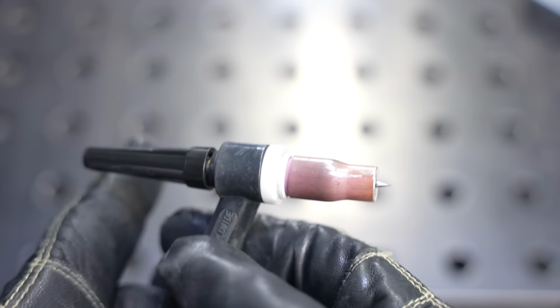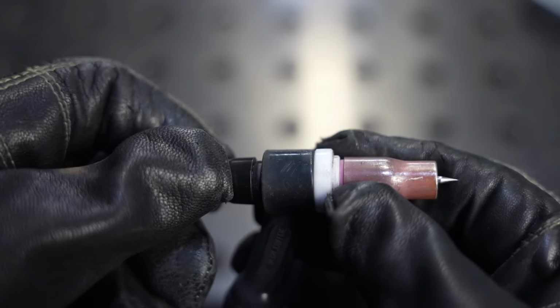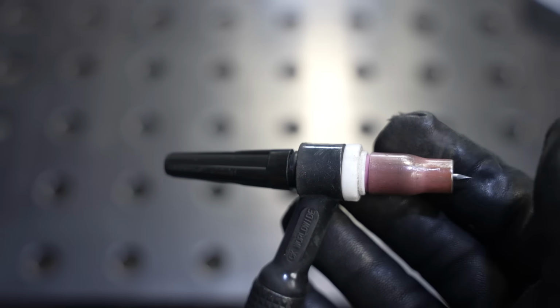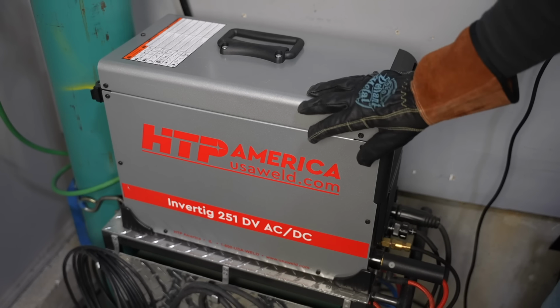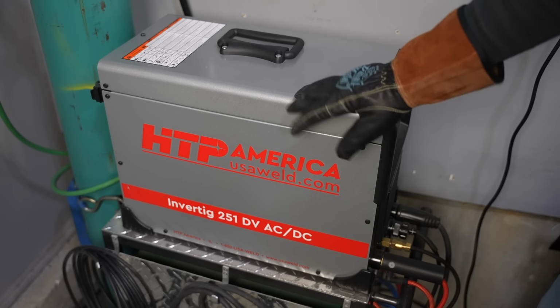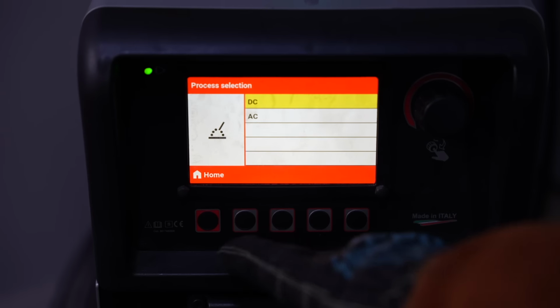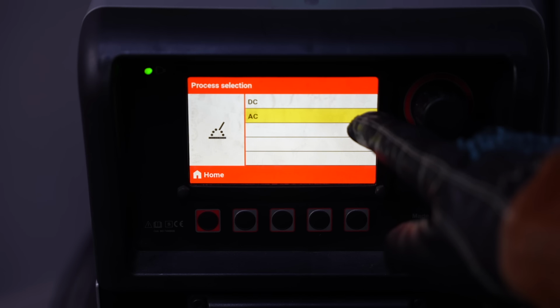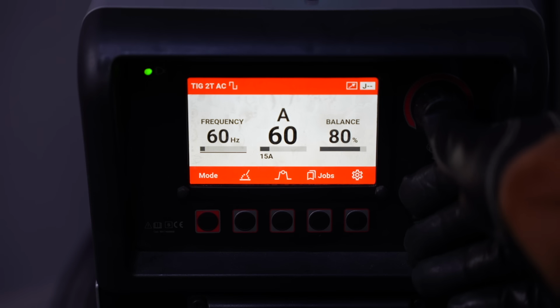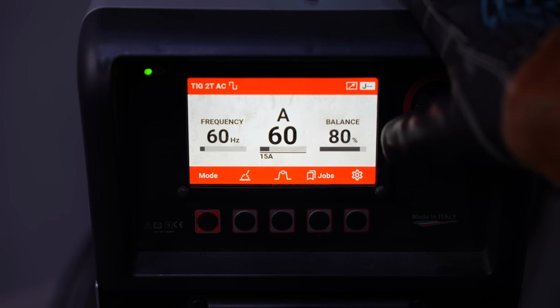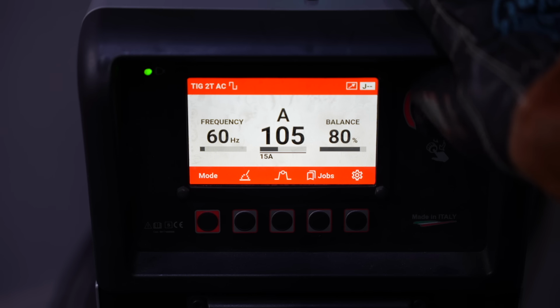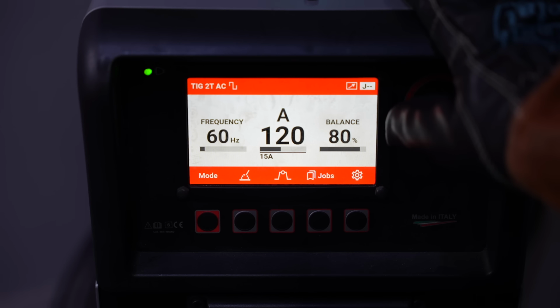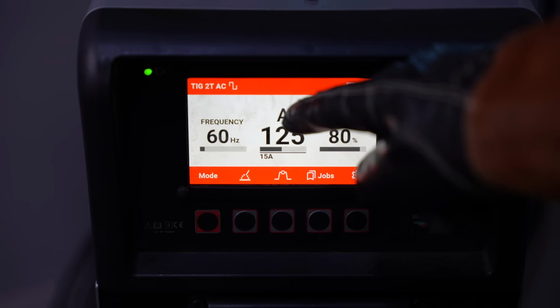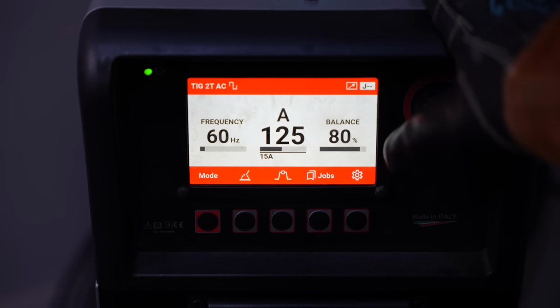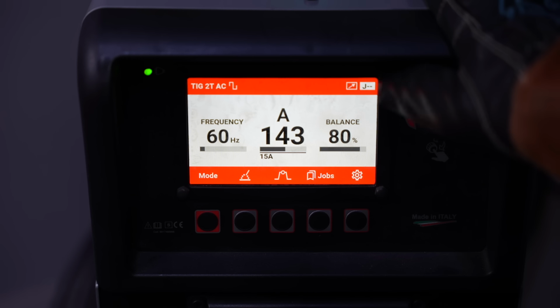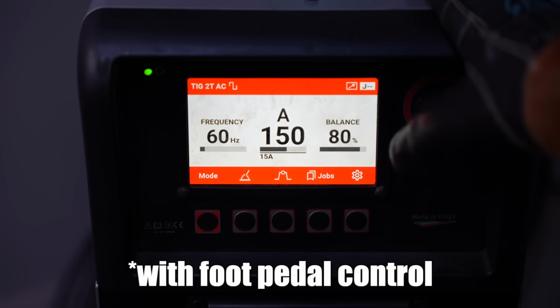Now, the actual extension of your electrode is going to depend a little bit on your joint type. This right here will be a pretty good middle of the road setup for me. This machine has all sorts of different ways that you can manipulate your waveform, but we're just gonna be using the basic setup here. When I go here, I can select AC, because I'm gonna wanna weld on alternating current with aluminum. And then I have 3 settings here: frequency, amperage, and balance. Now, amperage, a good rule of thumb is about 1 amp per thousandth of an inch. So 125 amps for some 1/8 inch thick material. Now, aluminum tends to suck quite a bit of heat, so I'll go over that by maybe even 25 amps here, somewhere around 150.